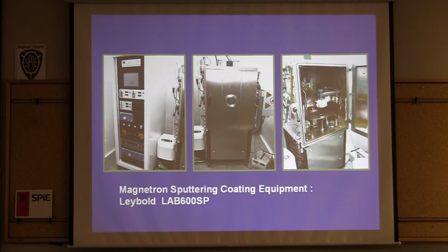This is our chamber. We have the sputtering chamber because the layers are quite thin. We grow the layers very slowly, controlling the thickness by calibration in advance, layer by layer. That way we can control the layer thickness. We have two systems: one for RF sputtering, another for magnetron sputtering, with three heads inside.